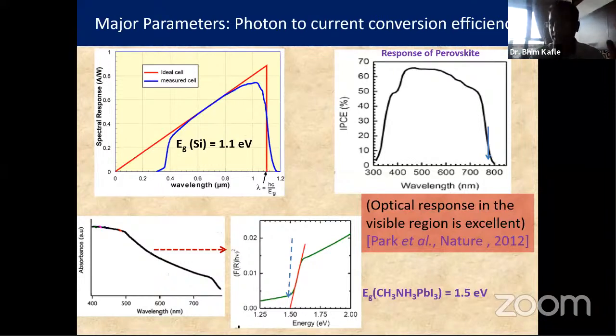If we have a material that can absorb mostly the visible and part of the IR, that would elevate the efficiency of the solar cell. In the case of silicon, its band gap is about 1.1 eV. It means that it absorbs not only the visible light but also part of the IR radiation, so its efficiency is very good. In the same token, if you look at the absorption curve of the perovskite, it absorbs visible light very nicely. Absorption decreases after 500, but it absorbs relatively nicely up to about 780 nanometers. After that, it goes down.